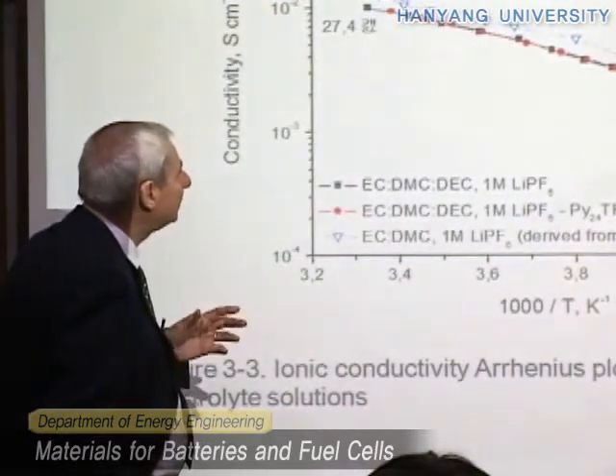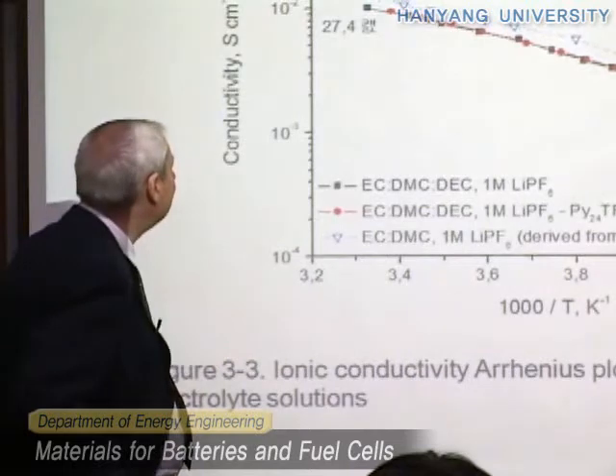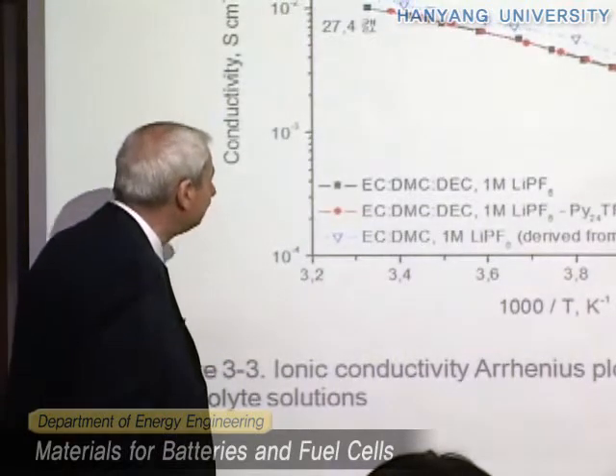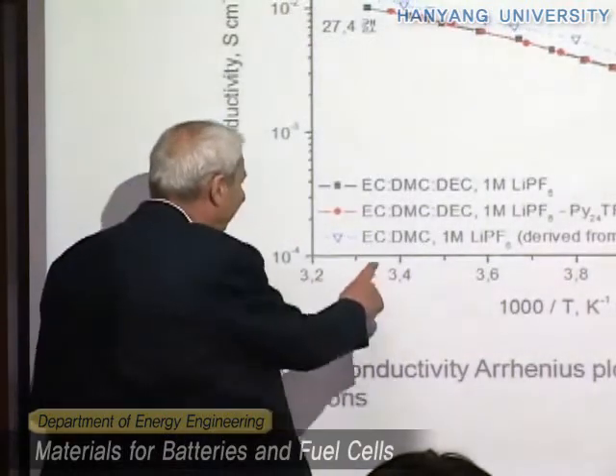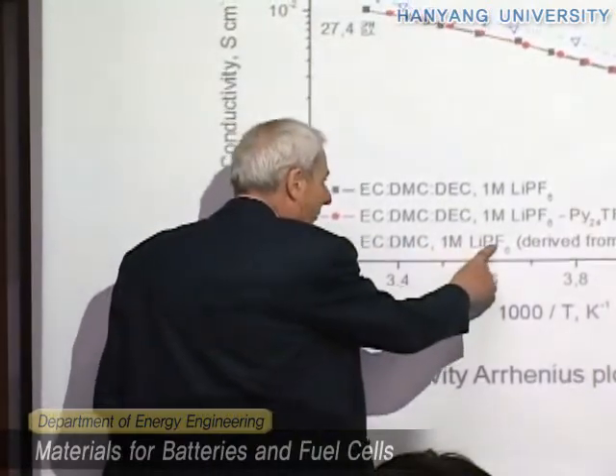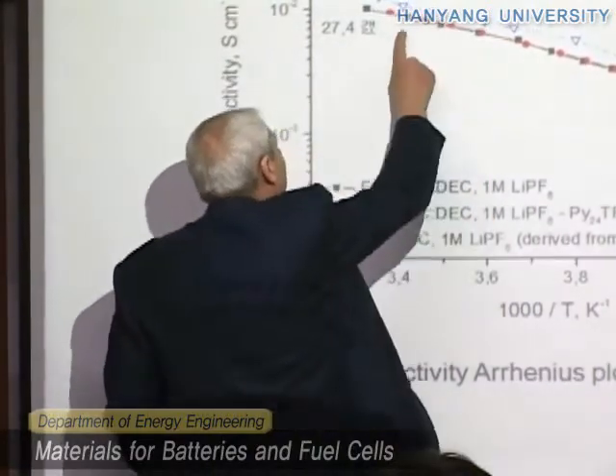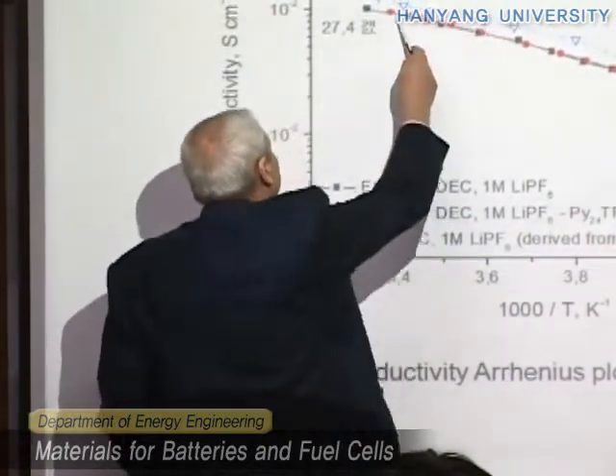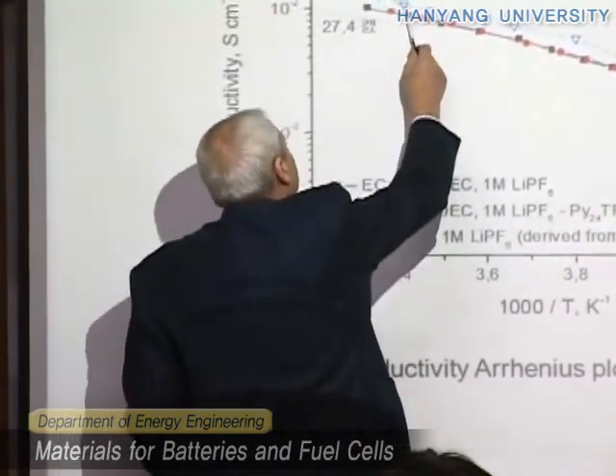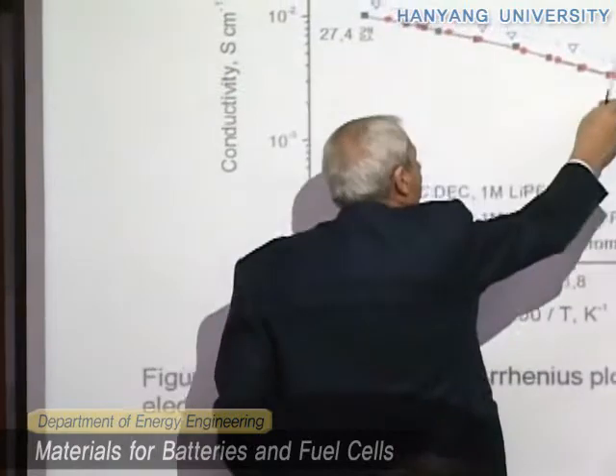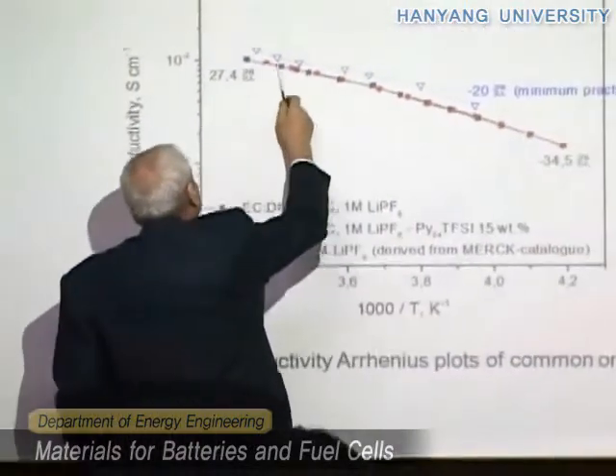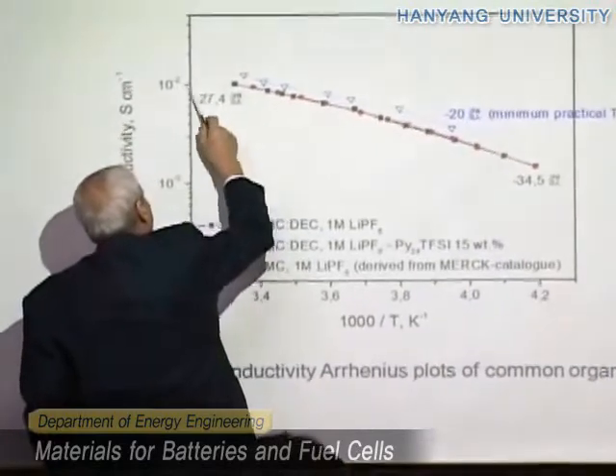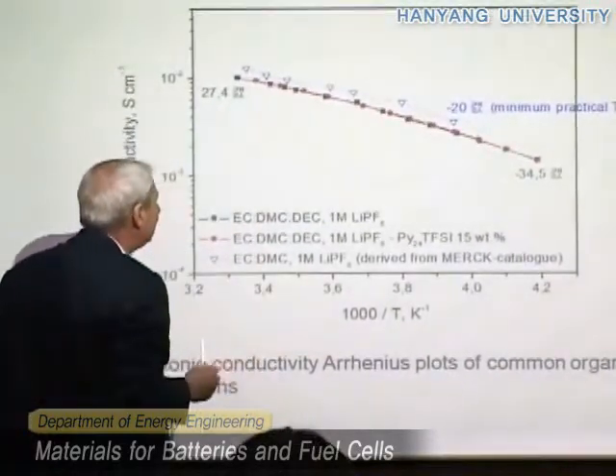We see that this is the typical solution, shown in blue here. The evolution of the conductivity is pretty good — it's very high, on the order of 10⁻² Siemens. But we cannot go below minus 20 degrees, because at that value we have solidification of the solution, so it doesn't conduct anymore.